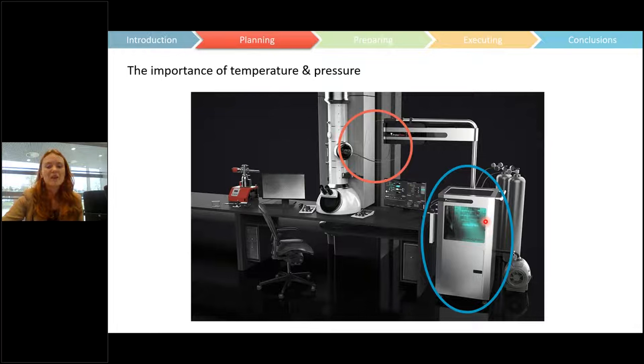So we like to run all of our reactions at 1 bar, and we like to run all of our reactions with a drying step first of at least 100 degrees to remove any physisorbed or chemisorbed water from the surface if possible.